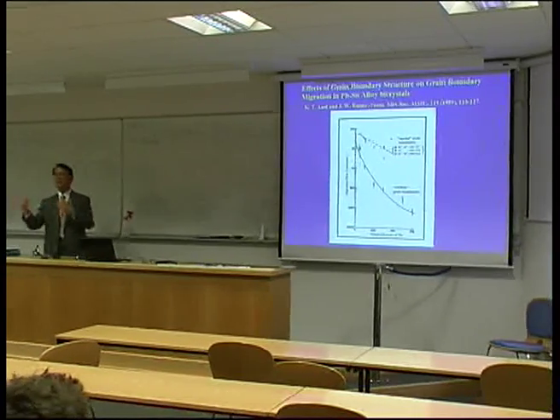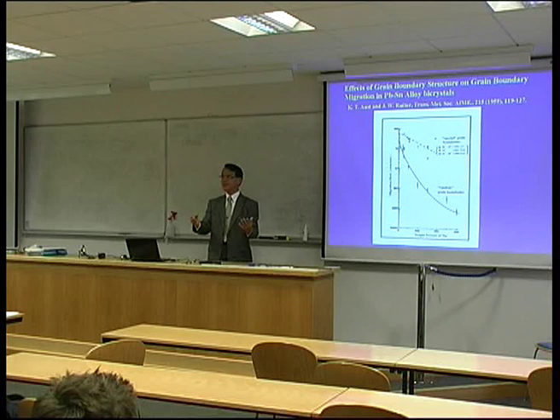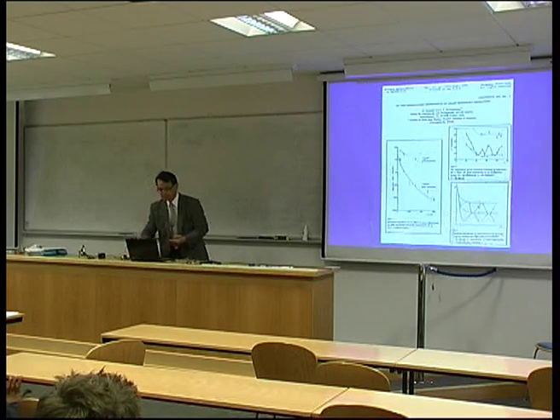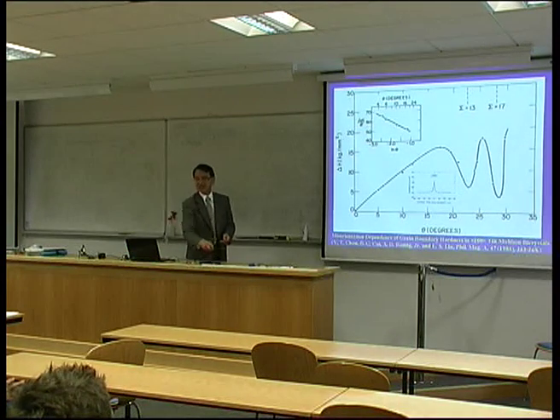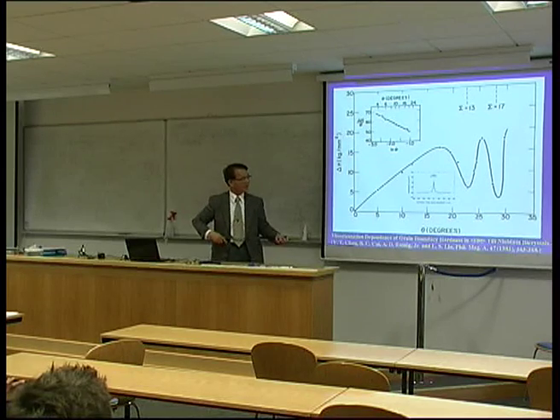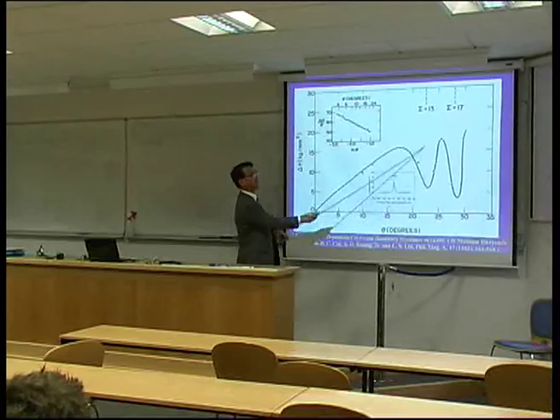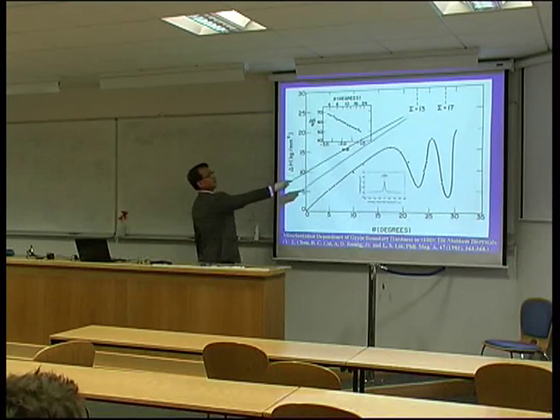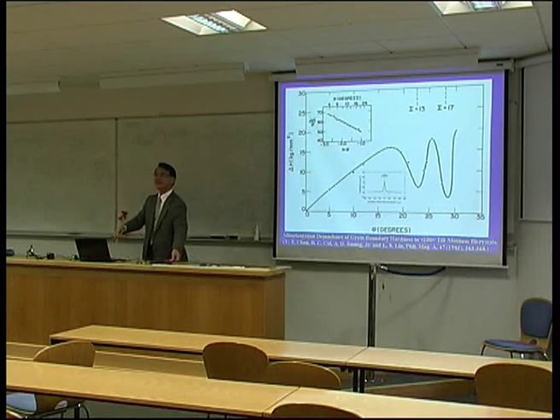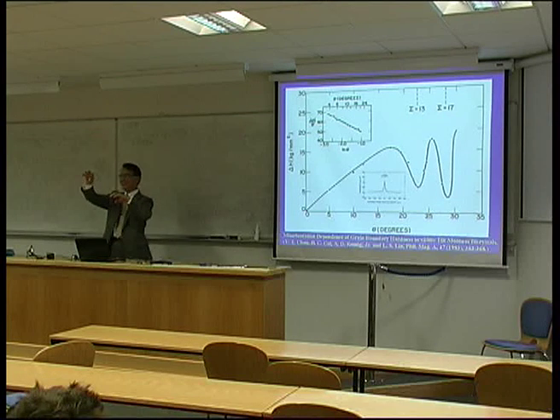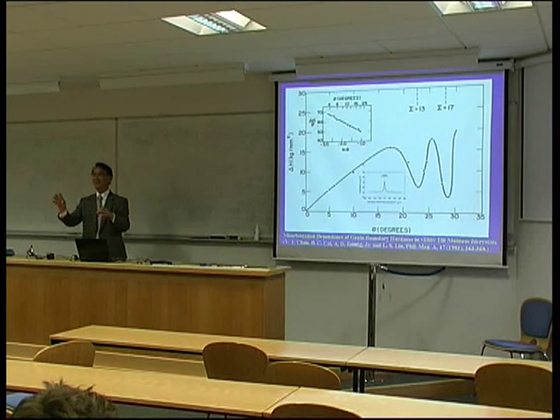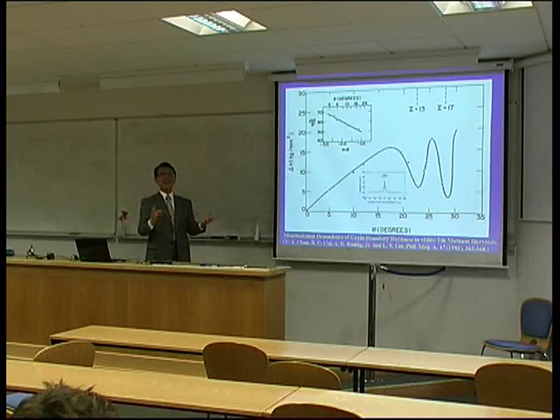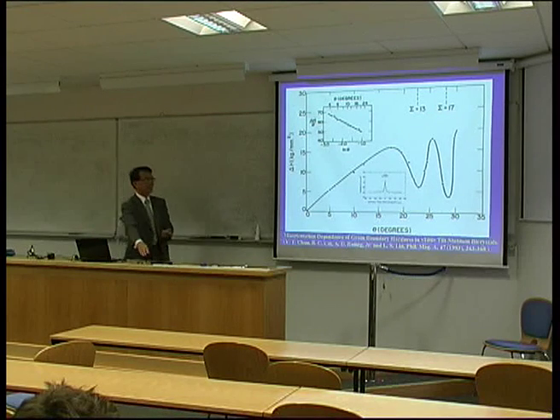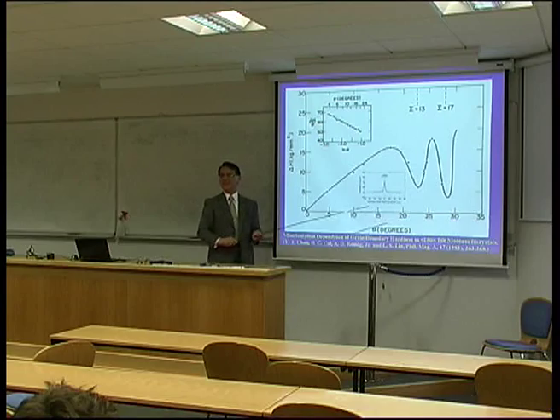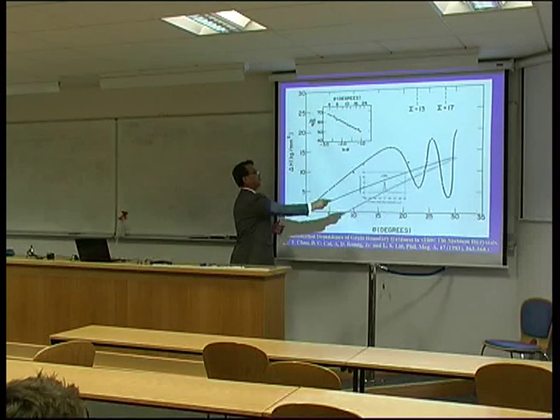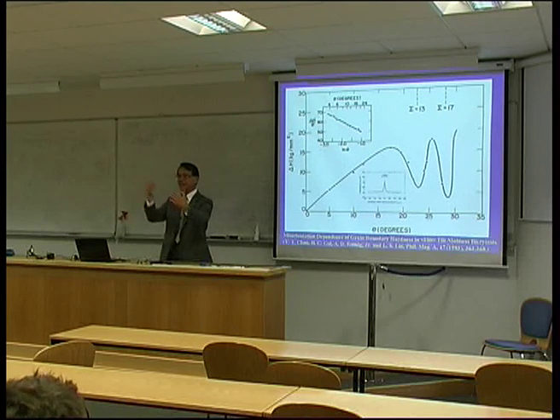So how we can control the microstructure, we also have to know the effects of impurity and grain boundary segregation. But anyway, for example, even for hardness, if you put an indentation on the grain boundary, the grain boundary hardness can change like this. Some special boundaries show very low hardness. So in real polycrystalline material, such different grain boundary behaviors are summed or agglomerated. And if you discuss only the average, you ignore such special effects. But if you take such different behavior more carefully into account, you can produce different polycrystalline material.